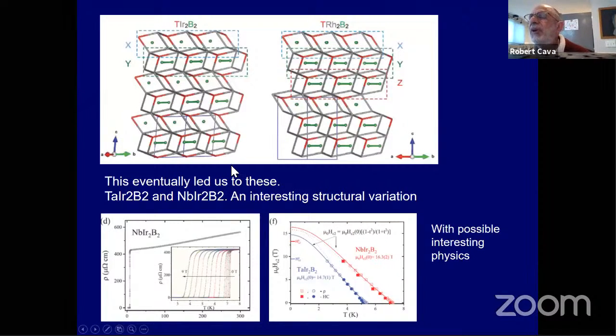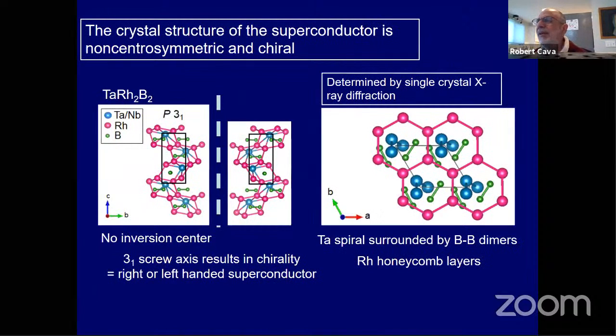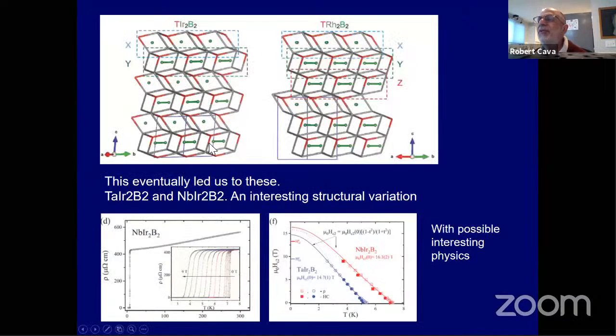And a big trick, which I hope to transmit, is that you often want to abstract. The crystal structure can look complicated and crazy. And you look at it, you go, I don't understand what's going on there. But you can abstract parts of this crystal structure so that you understand what's happening. And then if you make a simplified drawing, which is what this is, you can see that the original superconductor, which is actually here, the rhodium one, is made up of blocks that go 2 blocks and 1, then 2 blocks and then 1.